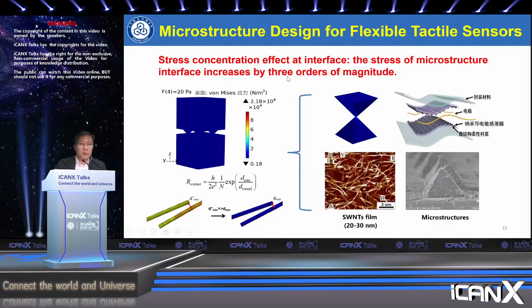From this simulation, we can see that if you design a microstructure at the interface of the flexible devices and cover it with very thin nanomaterials, for example, single-wall carbon nanotube networks, there is a stress concentration effect at the interface. The stress at the microstructure interface will increase by about 3 orders of magnitude, which will dramatically increase the contact resistance change, even under a very tiny pressure or pressure change.